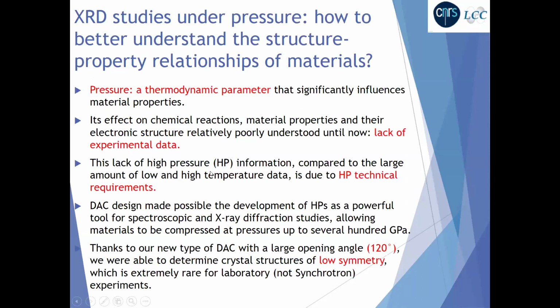So, X-ray diffraction studies under pressure is a powerful technique to better understand the structural property relationship of materials. If we consider pressure as an external stimulus, it is a thermodynamic parameter that significantly influences material properties. But its effects on chemical reactions, material properties, and electronic structure are relatively poorly understood until now, probably because of a lack of experimental data. This lack of high pressure information, compared to the large amount of low and high temperature data, is due to the high pressure technical requirements.